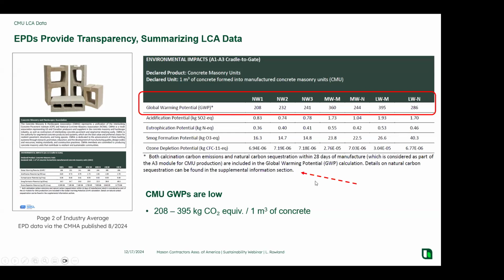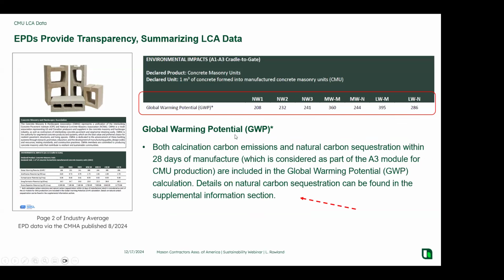However, there's this very important footnote associated with a declaration. The footnote will tell you that the global warming potentials for these products include the calcination carbon emissions, which, remember, that calcination emission comes from the cement plant. When I drive off the CO2 associated with the limestone, that's a calcination emission. It includes the calcination emissions from me, but it also includes natural carbon sequestration. Essentially, and I'll go through it here, what happens is you have the plus emission associated with the calcination, but you have a minus associated with that sequestration through carbonation.